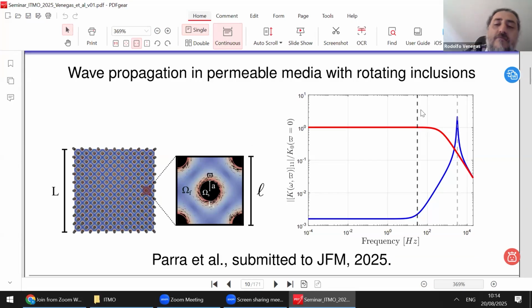Yes, in particular, for this example the cylinders were of sub-millimetric size, but we have done some simulations for materials with larger cylinders, about 4 centimeters. And what happens there is that this peak goes down in frequency. In this example it is nearly 2,000 hertz, but for 4 centimeters, it's about 50 hertz, 100 hertz. And it will be part of Claudio's PhD thesis to work out the experimental validation of this. So it's within our plans to do it.